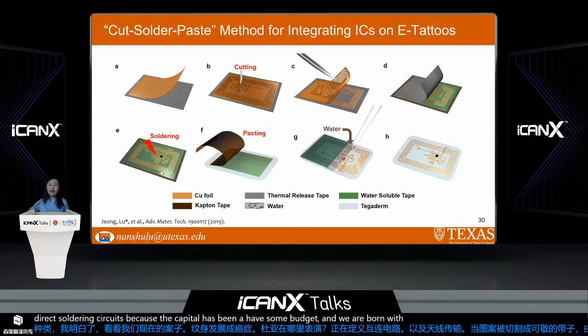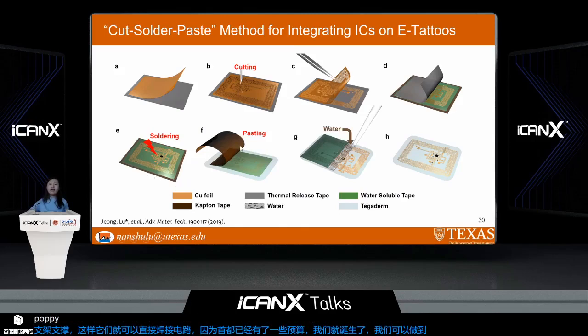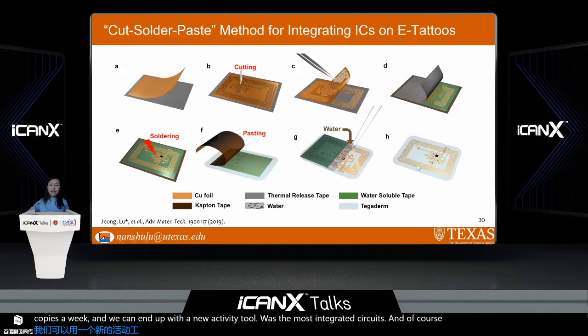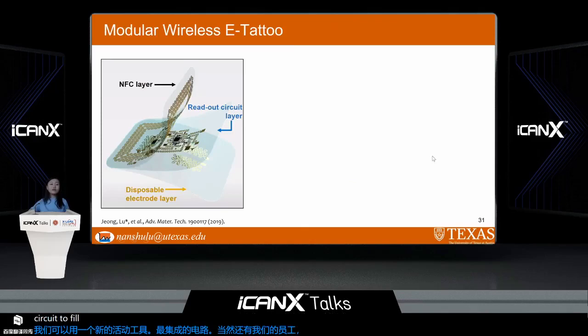And because the Kapton has very high thermal budget, we can do the pasting and then water-soluble tape dissolving. And at the end, we can end up with an active e-tattoo with those integrated circuits. And we can, of course, stack up multiple layers of this active circuit to form a completely wireless e-tattoo with a disposable electrode layer, readout circuit layer, and NFC layer, for example.